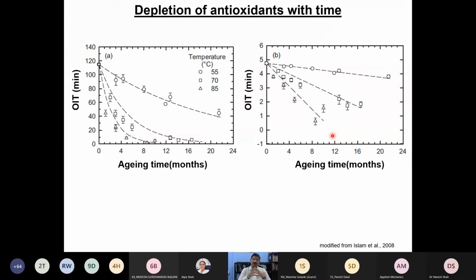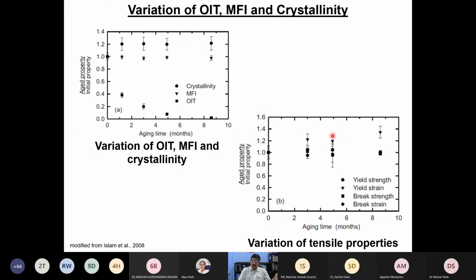So basically, why have we done this at various temperatures? Because if I am conducting a test at 25 degrees, I may have to wait for my entire life in order to see a significant change. By increasing the temperature, we tried to see accelerated aging, and by using Arrhenius modeling, I can always back calculate what can happen at 20 degrees or 10 degrees. So this is the concept we have used.